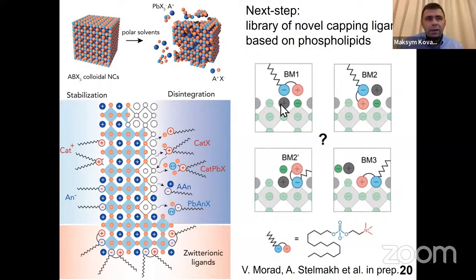Without going too much into detail, I will just tell you that we tested several possibilities, such as attachment of a ligand simply by adhering to the surface, or displacive attachment, which we initially assumed, where the phospholipid displaces a pair of ions and incorporates itself into the AX-terminated 100 facet. So our conclusions are that this binding mode 3 is much more likely than any other one depicted on the slide.